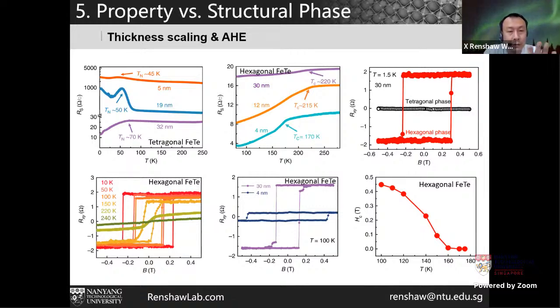No problem. On the upper left side, that is a thickness scaling for the tetragonal phase of FeTe. We vary the thickness from, for example, 30-something nanometers to 5 nanometers. For 30 nanometers, we have a Néel temperature around 70 K. Then if we lower the thickness, the Néel temperature goes lower and lower; for 5 nanometers it goes down to 45 K. This is expected because as the thickness goes lower, this long-range magnetic order is harder to survive.